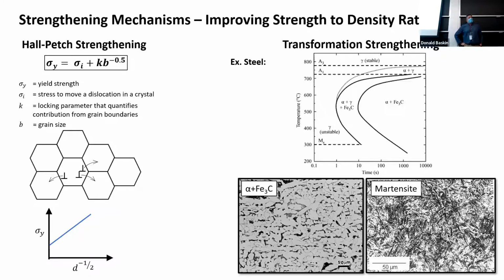And I think the reason this works is that you have dislocations that are inside the grains. It takes more energy to get a dislocation to traverse a grain boundary than it does just to go through a grain. So you have many more grain boundaries because the grain size is smaller. Then you can make it that much more difficult because the dislocations have to jump over more grain boundaries, right? And that's more energy, that's higher strength. But you've got to be careful with this one because the size of grains will grow with temperature and time because there's a lot of energy associated with having all that surface area, with all those grain boundaries.